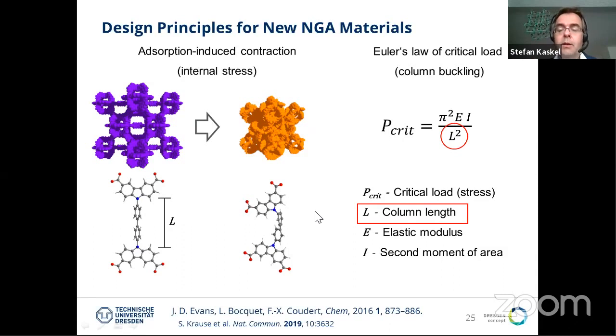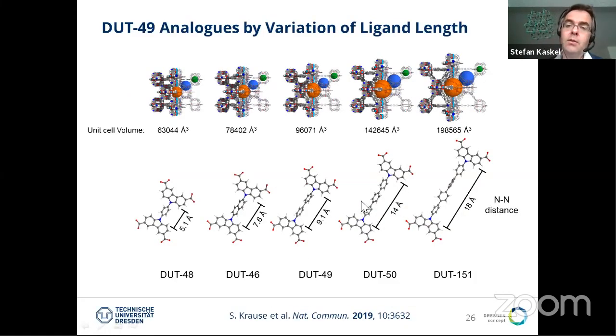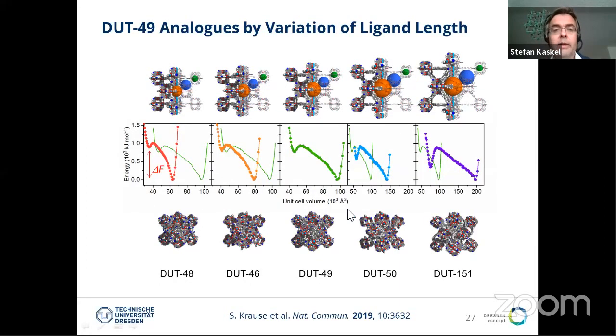So this is where the synthesis chemist can do something. We can change the length of the column by just making longer linkers. And Simon Krause in his PhD studied this behavior from a very short linker to a very long linker. And these are the labels of these type of materials. And you can see these are the predicted, and some of them are also single crystal structures that we have received here. And you see that the pore is going bigger and bigger. And with this type of isoreticular series, we can understand what is the impact of the column length. So this again shows the potential of in silico design.